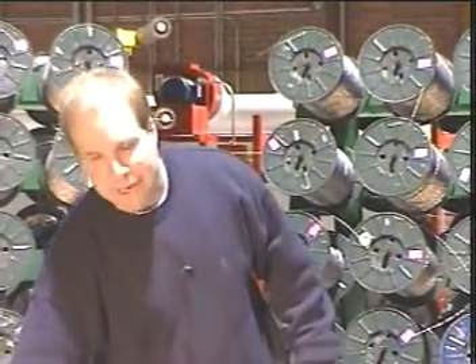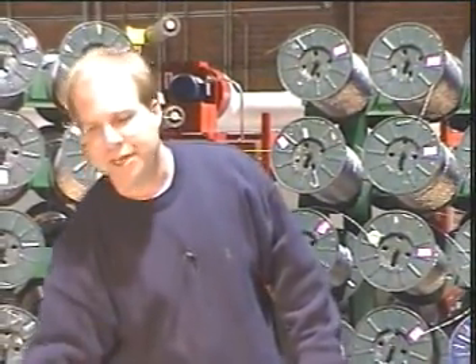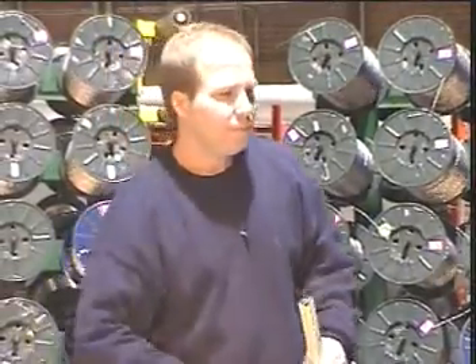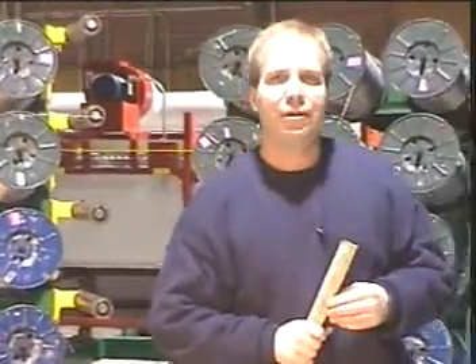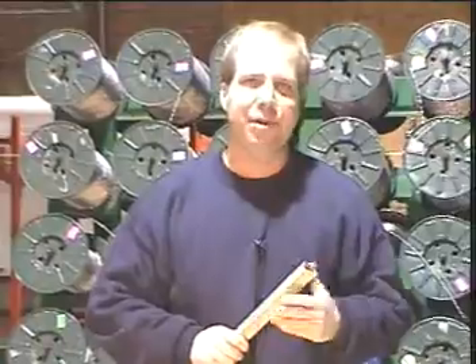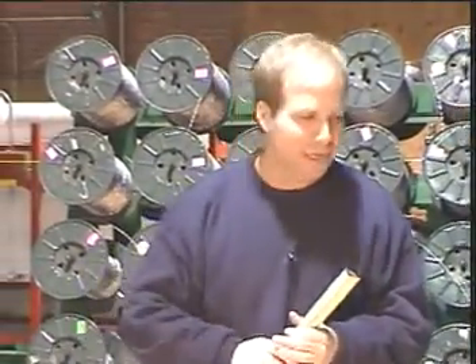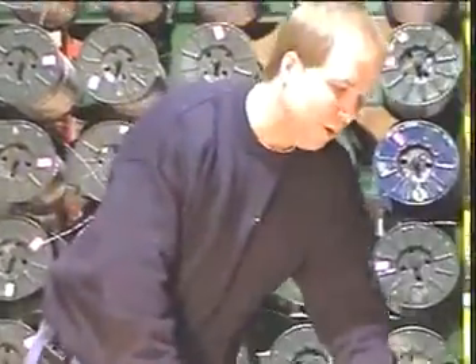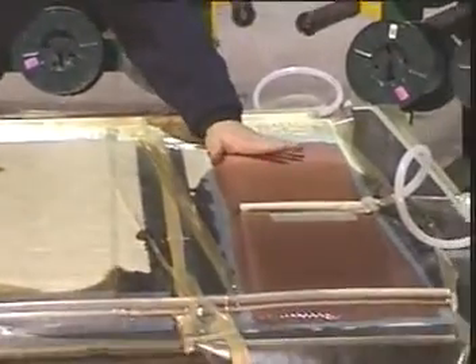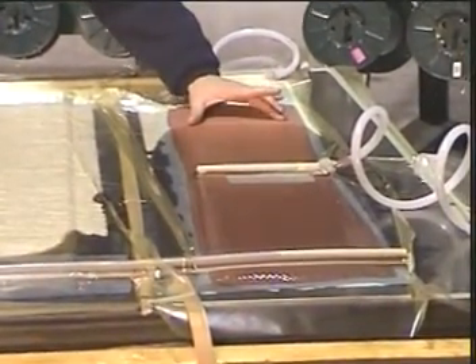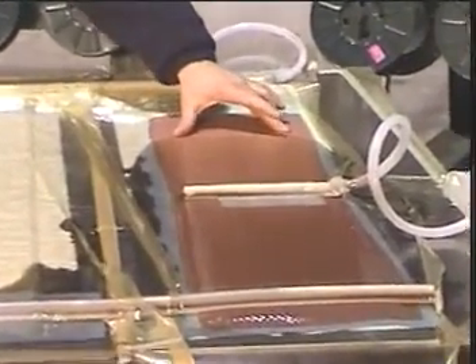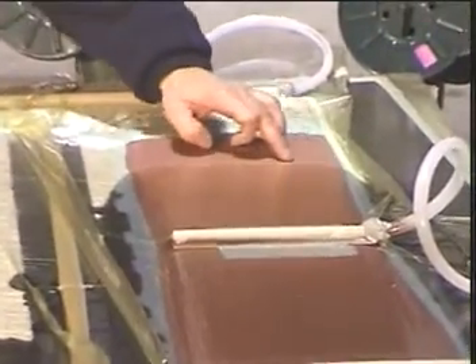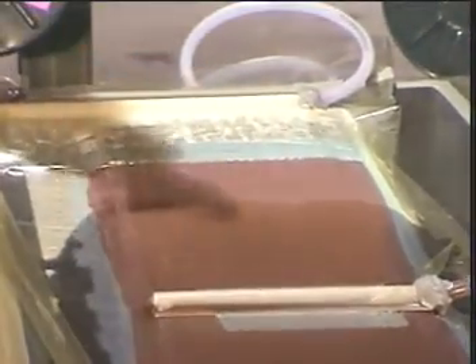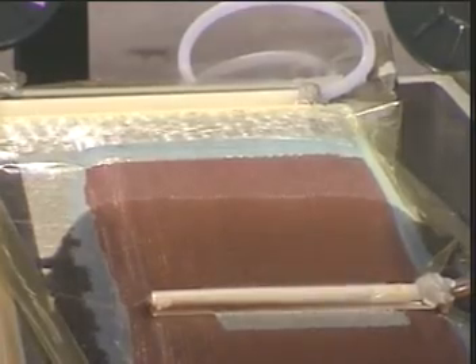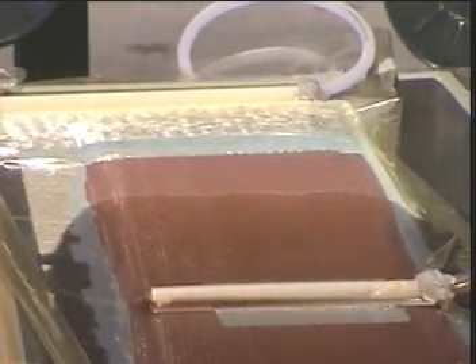Again, if we had a highly heated tool, we could kick the heat in, the heat would transfer, we'd begin the cure. I'm going to come back over one more time to our scrimp panel now that these are finished. And I just want to show you, this is what we really see when scrimp runs out of gas. In infusion media, because it is so impermeable, combined with the glass, now we're really starting to slow down to the point we might have to fire up a second feeder, which is more tubing, more wasted resin.